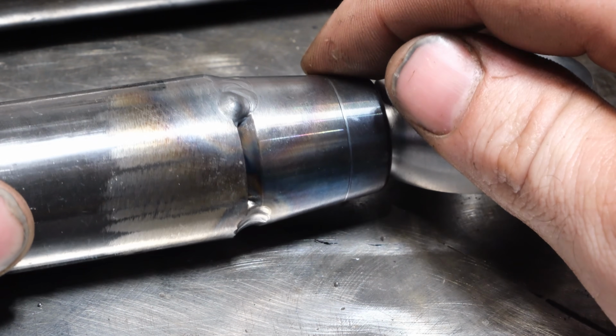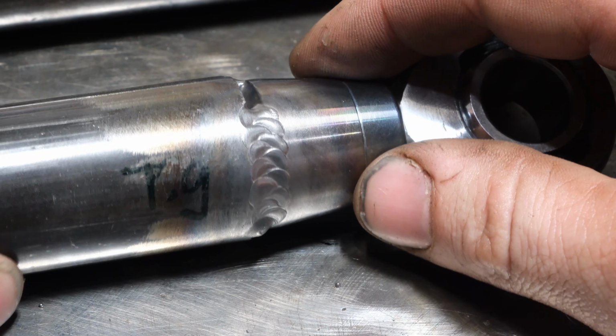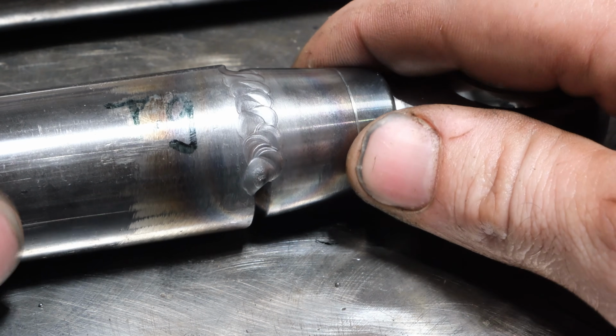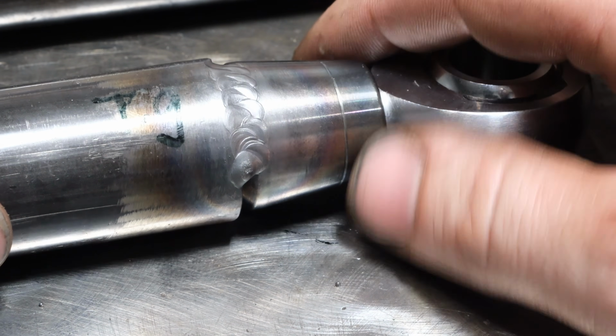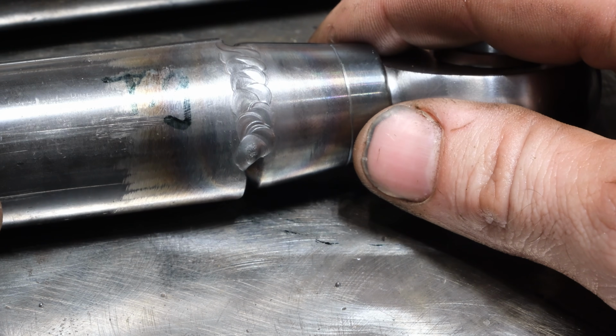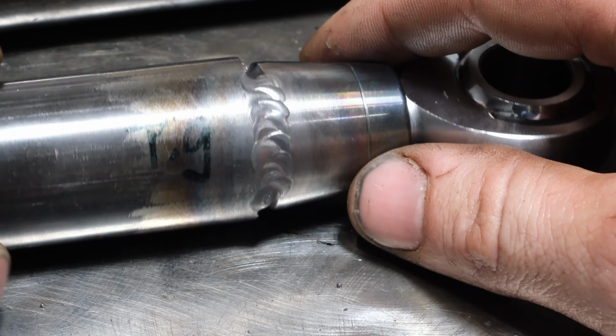You can see that it's not concave. We don't want concave. So that overall looks good for a short weld, two passes. This should fare fairly well in a cut and etch when we look at it. Now let's look at the MIG welds.